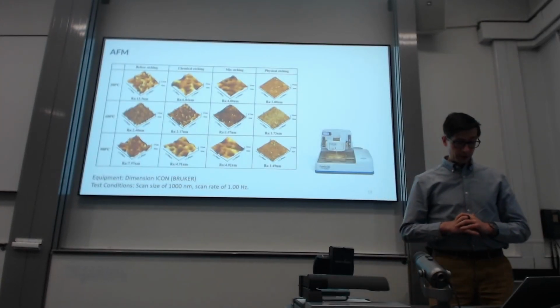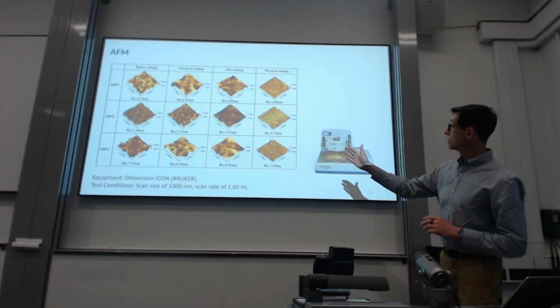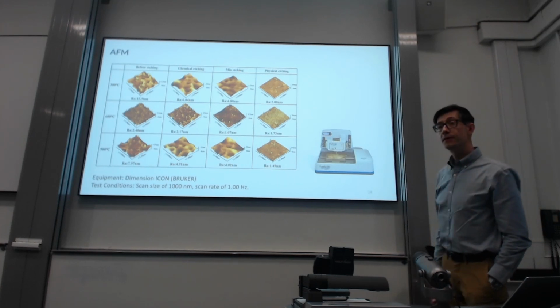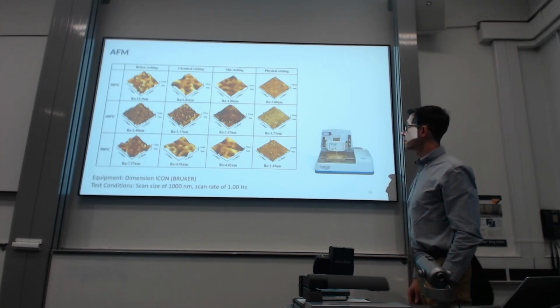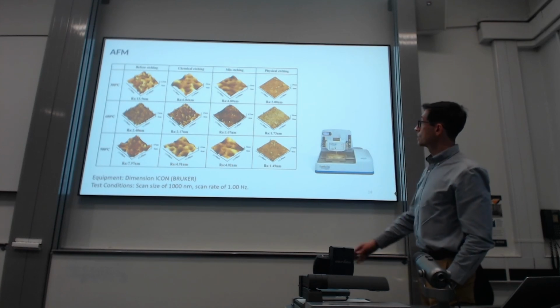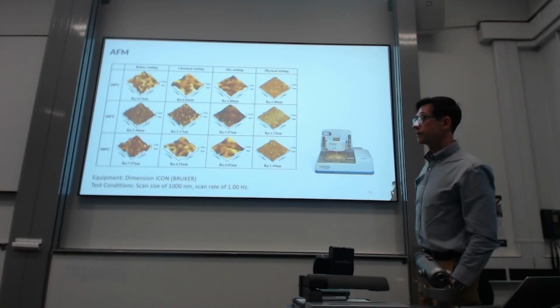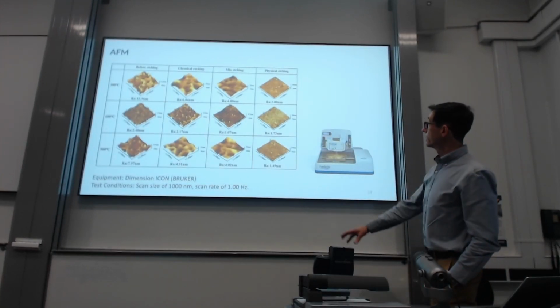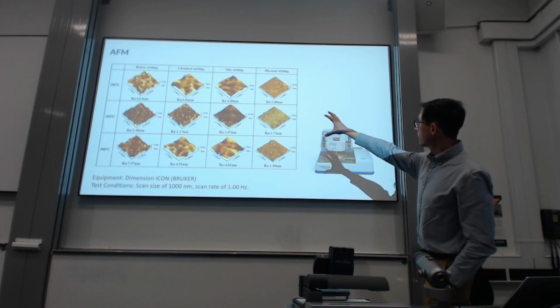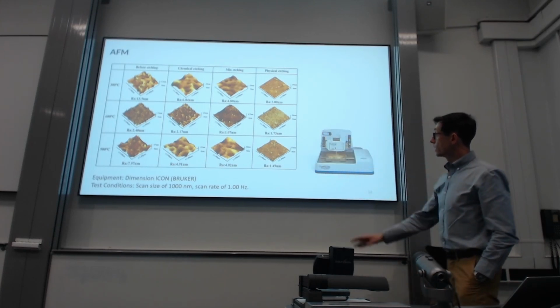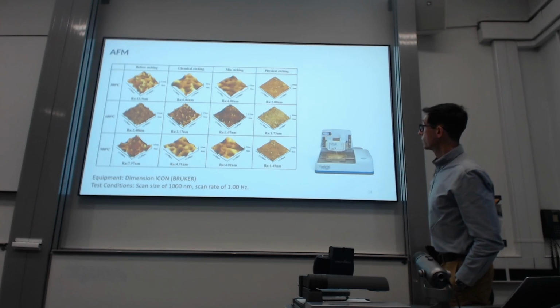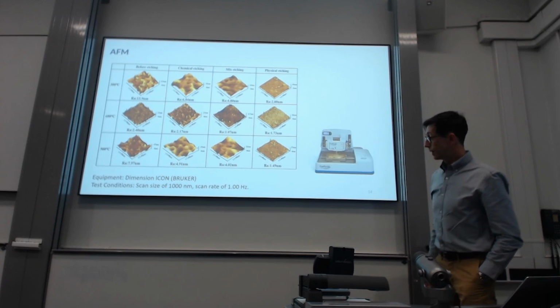Before I move on to mechanical characterization, it's also worthwhile looking at the AFM imaging and results of the surfaces. So before etching, this is the surface morphology that we start with, and then after chemical, physical, and mixed etching cases, we can see surface morphology altered quite significantly, especially in terms of the physical etching. The surfaces tend to be much smoother.